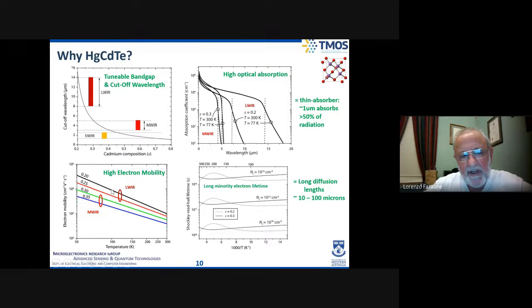And so if you look at this mobility and this lifetime, mu and tau, and calculate the diffusion length for those two numbers, you get a diffusion length on the order of 10 to 100 microns. What that means is when I generate electron hole pairs, those minority carriers which end up being the photocurrent in the detector, can travel 10 to 100 microns before they recombine.